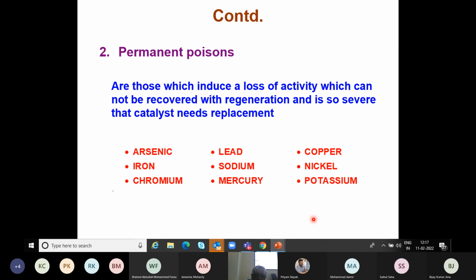The permanent poisons are, of course, the heavy metals which might be there along with the feed. These are at the ppb level, parts per billion level. But over a period of time, let's say 5 years of 24 by 7 operation, quite a significant quantity of heavy metals get deposited. That leads to a slow loss of activity, and this cannot be recovered. So the catalyst needs replacement.